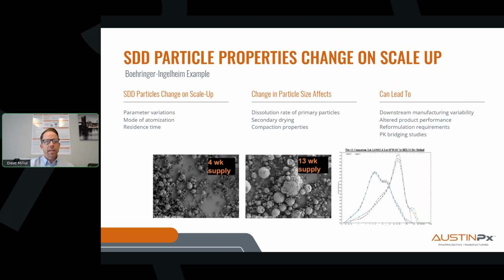And the variability isn't just a nuisance, it can lead to major manufacturing and product inconsistencies. In some cases, the product's bioavailability changes enough that you have to go through reformulation and PK bridging studies that can add significant time and cost to the program. We've put some SEM images and a particle size distribution figure below from one of our partners, Boehringer Ingelheim. This is exactly the issue they were dealing with going from small batch to large batch supply, and the drastic changes in particle size and morphology were causing significant dosing and performance issues.